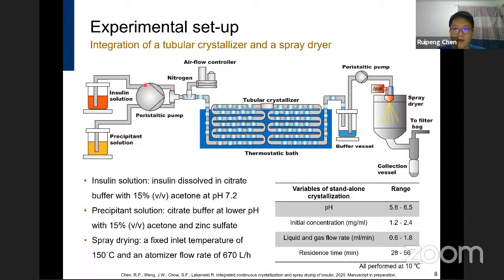And then a peristaltic pump was used to transfer the two solutions into the tubing via the first static mixer. And the nitrogen was incorporated into the liquid using an airflow controller via a second mixer, which is placed around 3 centimeters downstream of the first static mixer. The tubular reactor was composed of 2 pieces of tubing, each 40 meters long, immersed in a thermostatic bath for temperature control. Therefore, the supersaturation can be generated by both cooling and the pH shift.